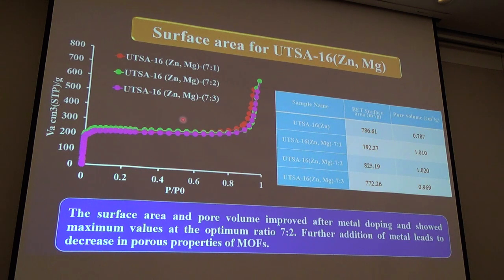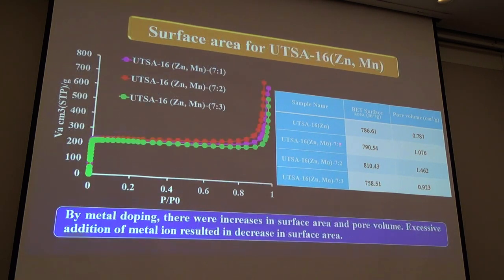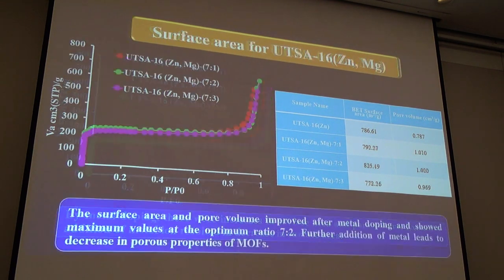Porous properties of the MOF were estimated by using the surface area and pore volume. The surface area was evaluated based on the N2 adsorption isotherms measured at 77 Kelvin and 1 bar. As we see in the table, surface area of the MOF increases with increase in metal to metal ratio from 7:1 to 7:2. Surface area and pore volume show the maximum values at the optimum ratio of 7:2.